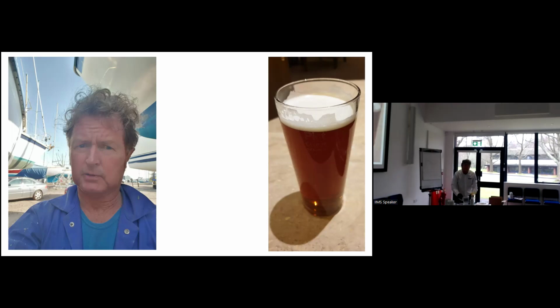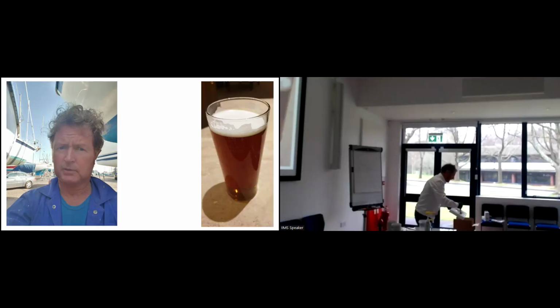So the first thing that one must do, and I should really be mixing this for 2 minutes. I normally count. I normally sing "Happy Birthday" 3 times. Use a brush to brush some resin hardener on. We call this 2-step bonding. And you can see, can't quite see in this light, but there is quite a strong colour change to the laminate. I get the feeling that you're almost creating like an end grain on wood, and the laminate is actually absorbing some of the epoxy.